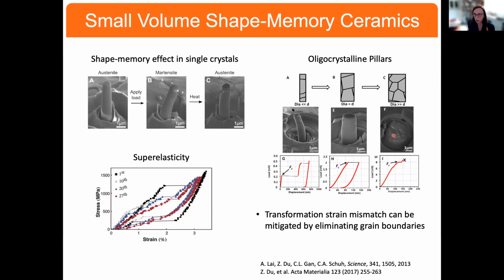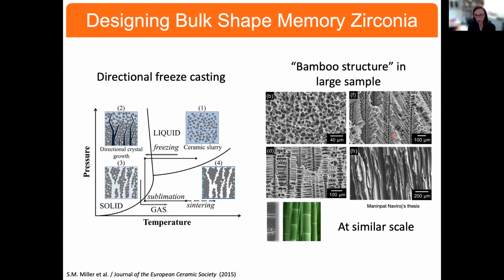So this gave us an idea. Couldn't we produce bulk porous shape memory materials and make the pore walls small enough that we would have single grain pore walls? And so we did this. Again, the idea is we did our directional freeze casting. Now we're looking at dendritic materials where we want to produce pore walls that almost look like bamboo structures, shown here in the bottom left.